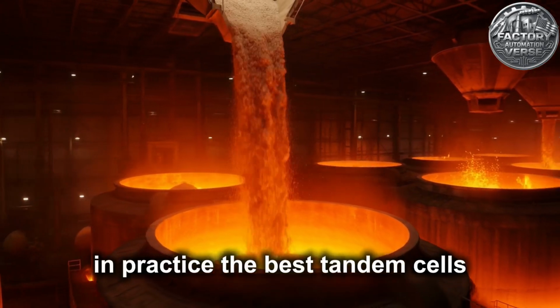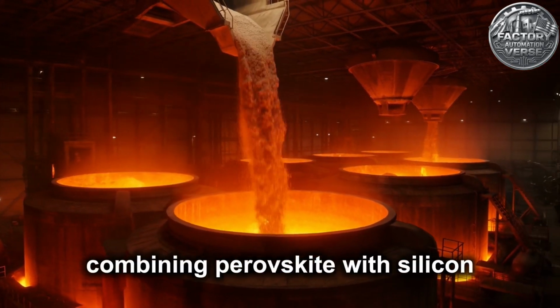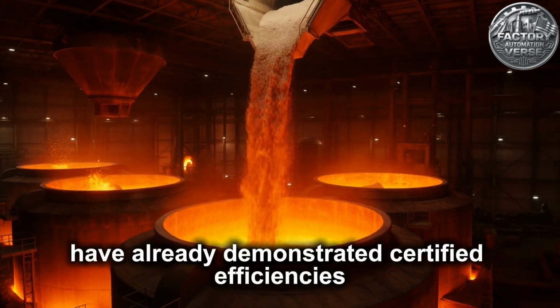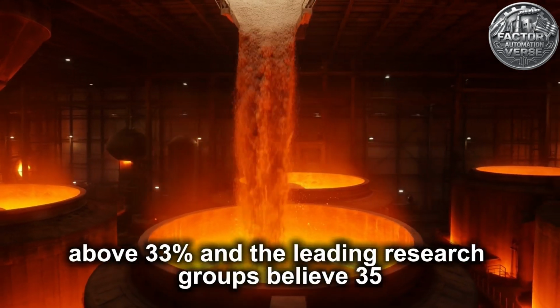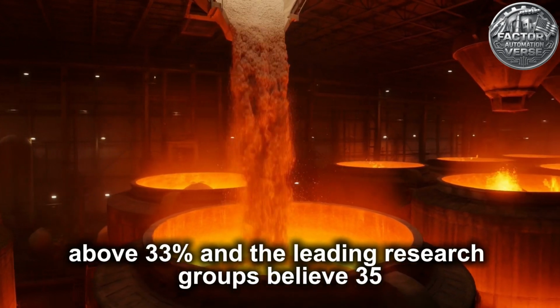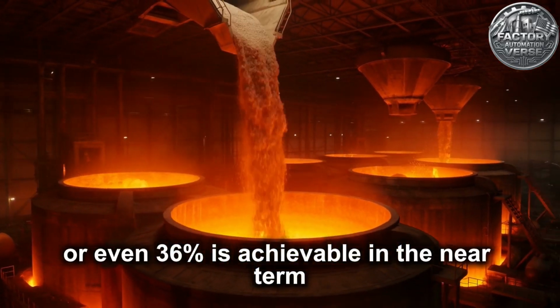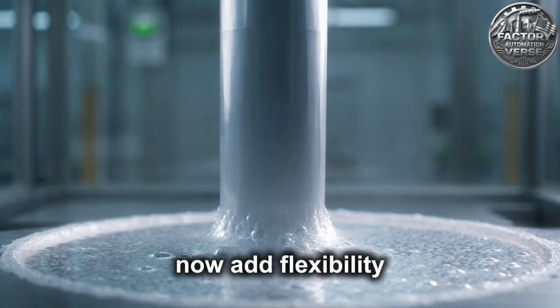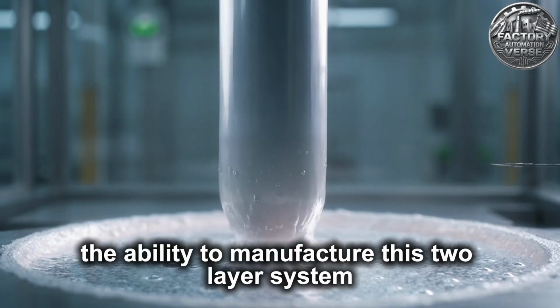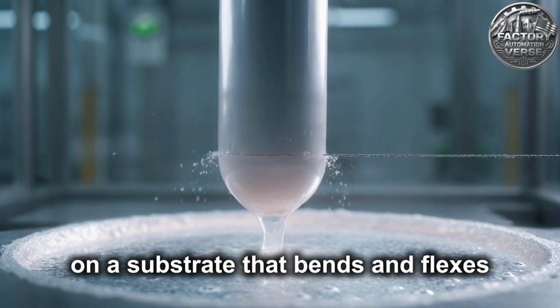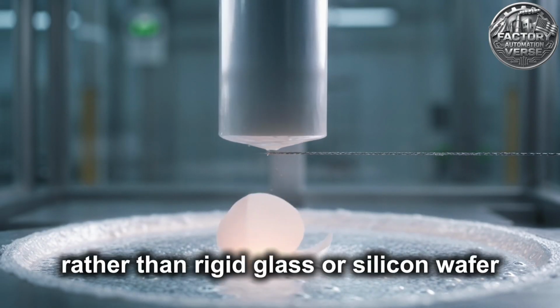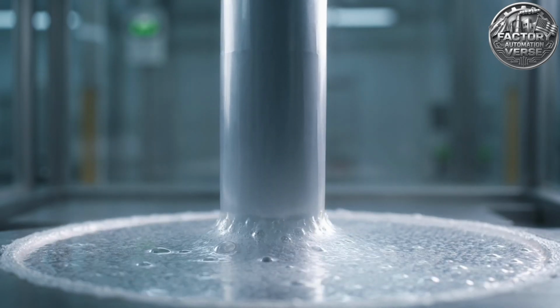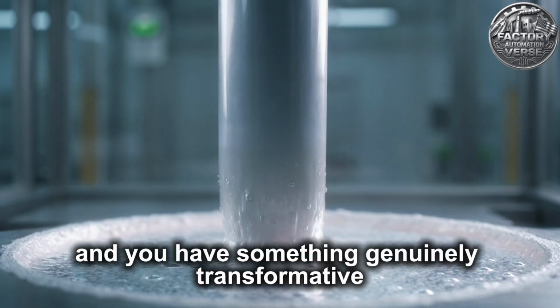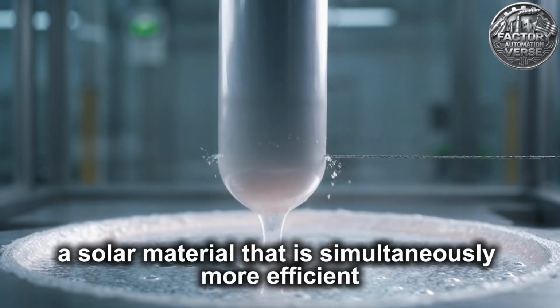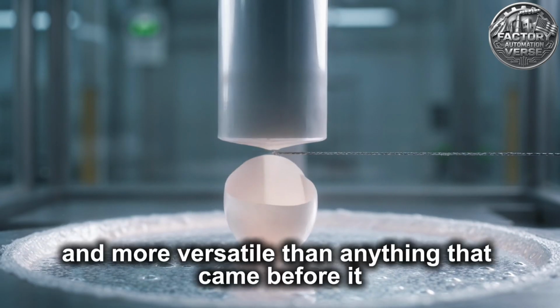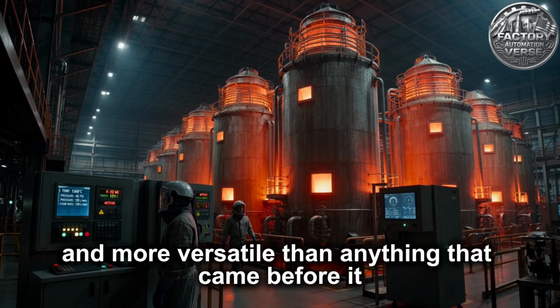In practice, the best tandem cells, combining perovskite with silicon, have already demonstrated certified efficiencies above 33%. And the leading research groups believe 35 or even 36% is achievable in the near term. Now add flexibility, the ability to manufacture this two-layer system on a substrate that bends and flexes rather than rigid glass or silicon wafer, and you have something genuinely transformative. A solar material that is simultaneously more efficient and more versatile than anything that came before it.